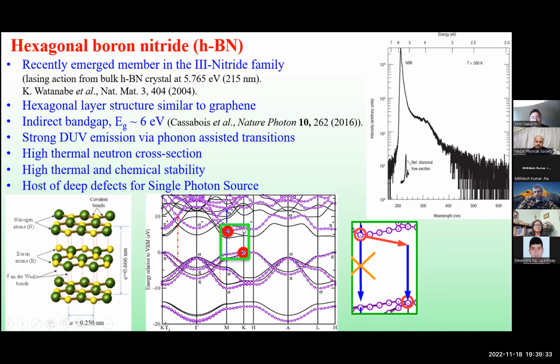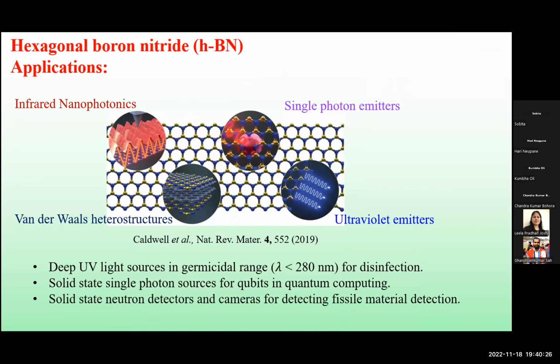So here is the band structure. The highest point of the valence band is in the K valley, and the lowest of the conduction band is at the M valley. Because it is an indirect band gap, the electron has to involve some phonon. The phonon in hexagonal boron nitride is very active, so it doesn't lose much energy as heat, and it still provides very strong emission around 215 nm. That strong emission can be used for UV emission.